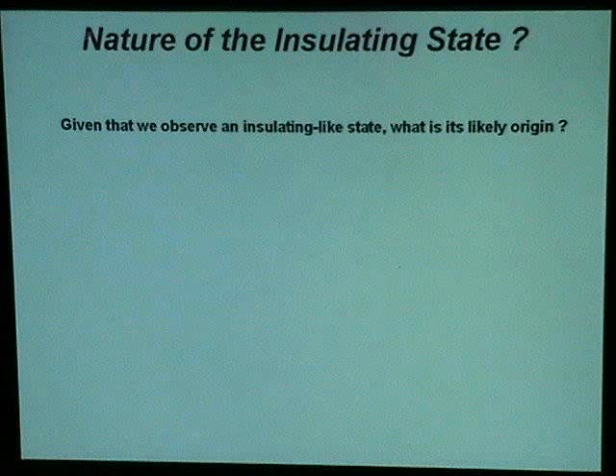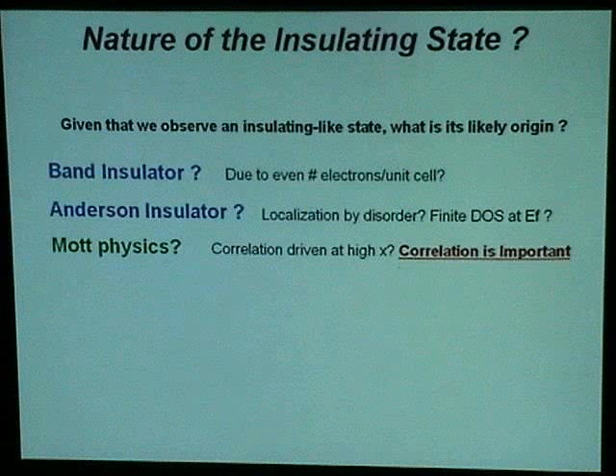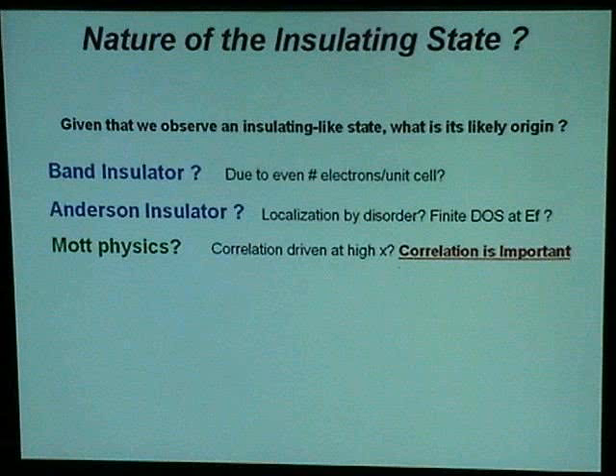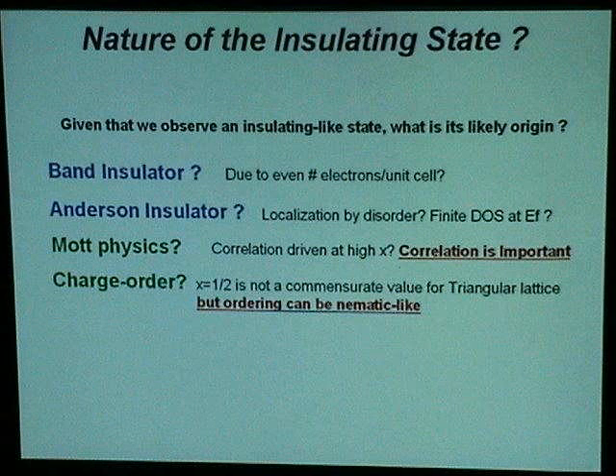So what is the nature of the insulating state? What are the possibilities? It's not a band insulator. Is it an Anderson insulator, localization by disorder, because the samples have some degree of disorder? But we do not see any finite DOS at the Fermi level, so it's not an Anderson insulator in that sense.